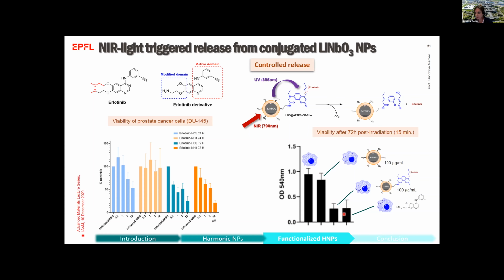And then here you can see the cells with the functionalized nanoparticle and the irradiation, and the cells with the inhibitor itself without the nanoparticles. You can see that the inhibition of cell growth is similar to the drug itself. So this was very encouraging results.